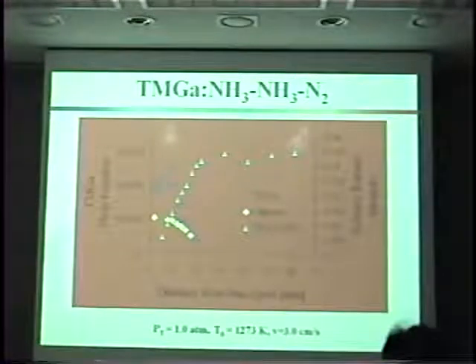What we did, first of all, we formed the adduct only upstream, and then under its own vapor pressure, we transported it in ammonia and nitrogen, and look what happened. So we have the adduct coming in, and at about this temperature, which is about 250 degrees C, the trimethyl gallium ammonia adduct starts to decompose. At the same time, you start to see the polymer appear, but you also see trimethyl gallium start to appear, because it's undergoing the reverse reaction back to trimethyl gallium and ammonia. Well, once the trimethyl gallium starts to appear, it also starts to attack the adduct to form more oligomer.